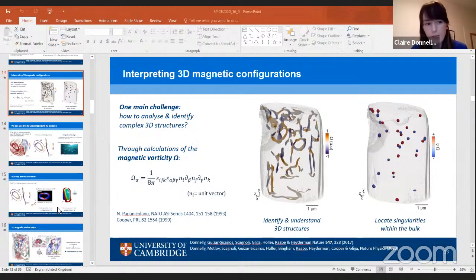This is obviously something we were looking for. We know that our sample is polycrystalline, so there are likely going to be grain boundaries and some pinning defects present. One of the tests that we did was we applied a number of field protocols. We saturated the sample and then looked at the remnant configuration after saturation. We also applied a thermal field protocol where we raised the sample up to about 400 Kelvin and again applied the saturating field. The interesting thing was that we saw different magnetic configurations and different vortex rings appearing after these field protocols, which indicated that they weren't purely due to pinning sites.